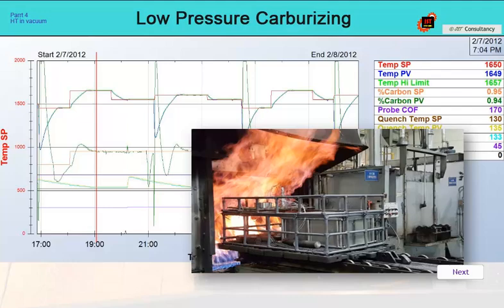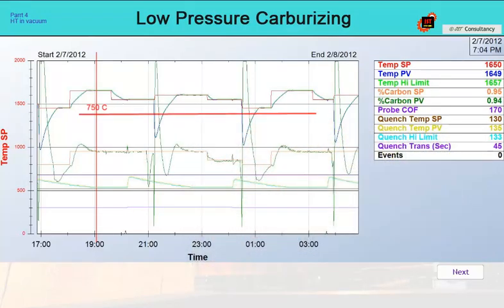At temperatures below 750 Celsius, the endo-atmosphere becomes explosive. This is not unusual when we load a batch into a preheated furnace. The temperature in the furnace after loading the batch often drops below this limit, and the furnace must be gassed with neutral nitrogen. The second risk is fire.